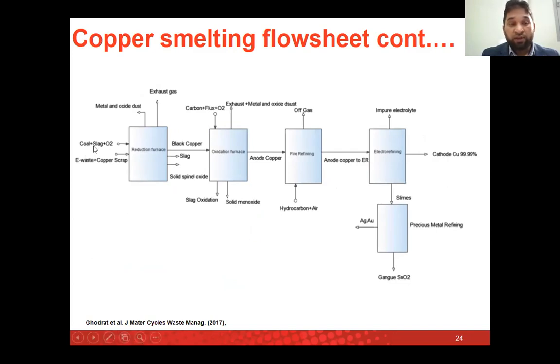So we give coal, slag, oxygen in there, and we have e-waste and copper scrap, and then it goes to the reduction furnace. We set the conditions for that: oxygen partial pressure, temperature, and all these things. And we have the outcome of this one: the metal and metal oxide dust, that is the first off, and then we have the exhaust gases. And from there we have black copper. Black copper will go into the oxidation furnace now.